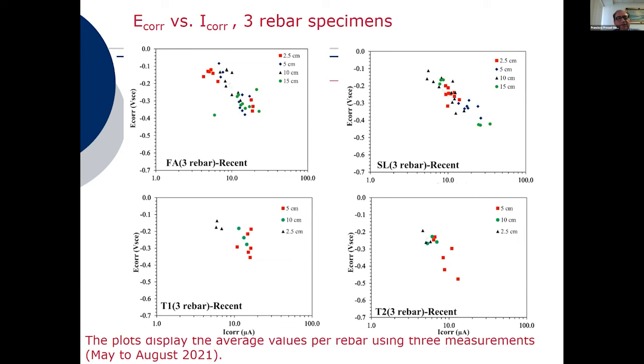In here, we have plots that correlate the corrosion current, now on the x-axis, versus the corrosion potentials, again for the 3 rebar specimens. And in this case, there is 1 outlier for the larger reservoir size, but all others appear to be in good correlation, which suggests that those that have the more negative potentials are the ones that are having the larger corrosion current, which makes sense. But interestingly, there are samples with the smaller reservoir that have comparable currents and corrosion potentials to those with the larger reservoir size.